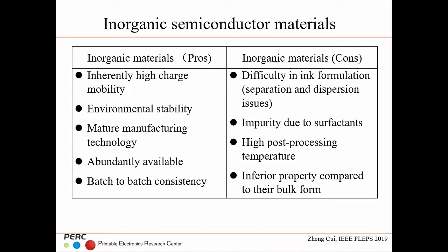And because the inorganic is environmentally very stable, it has manufacturing technology, is abundantly available, and has batch-to-batch consistency. But the problem with the inorganic, if you want to print it, is that it's difficult to make the ink. That involves separation and dispersion, and if you use the dispersion, you have to use a surfactant, which becomes an impurity. Then you have to use high temperature annealing to get rid of this impurity. And also, once you made the ink, you always have to go back to solid.